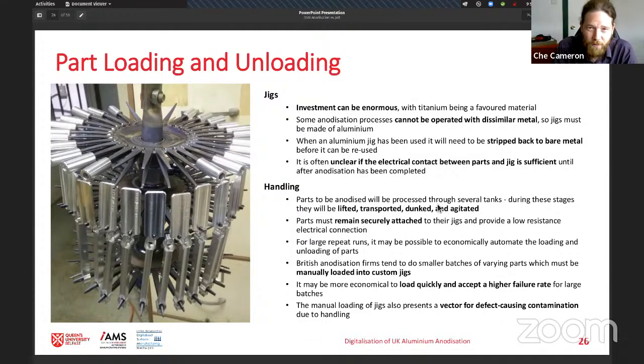And the contemporary work we see these days, and we heard earlier about some of the issues with basically the easy work being offshored and most surface manufacturing in the UK being technical and difficult. This leads to manual loading into custom jigs for a wide range of geometries, which is difficult to automate and takes more time. In some cases, if the run numbers are large enough, it's better to just quickly load reasonably well and accept a higher failure rate in a batch. But one of the issues too with the manual loading of jigs is you're introducing a vector for contamination again. And every single anodization company I talked to told me at least one anecdote about finding a fingerprint in the finish. And when I talk about a clean line, that's really what I mean. It's enough for you to just touch it with your fingertip, and that will destroy or it will compromise the anodized finish.